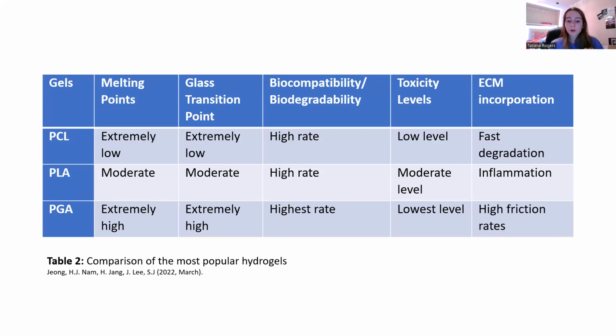strength. It is FDA approved, but the downside of PGA that I will acknowledge is that it uses glycolic acid, and glycolic acid causes a high friction rate, which could lead to the degradation of cells. But luckily, the company Dexon, which CellLink actually uses, has modified PGA with a Poloxamer 188 coating that reduces the friction within the tissues. And in the chart, I am currently comparing the most popular hydrogel links on the market.